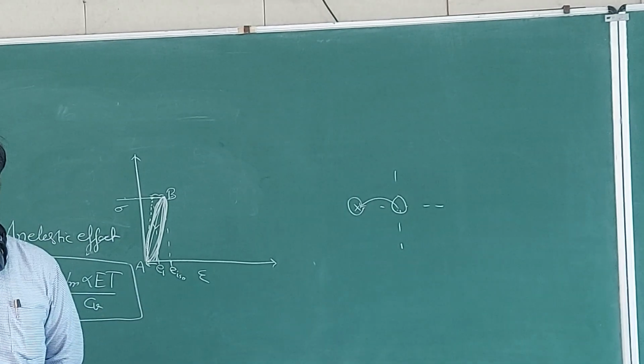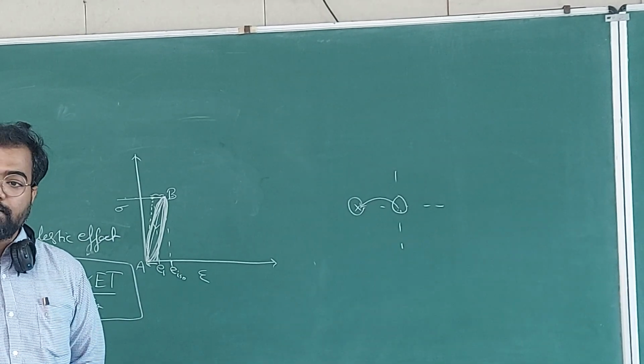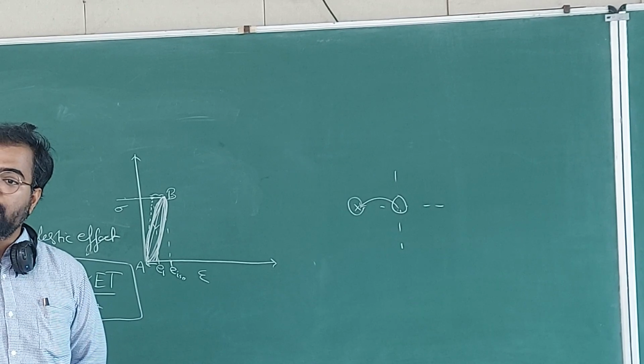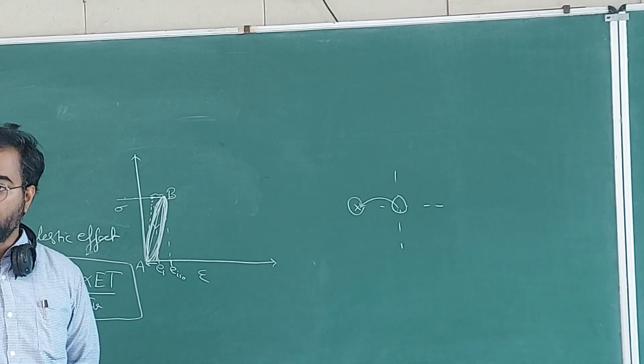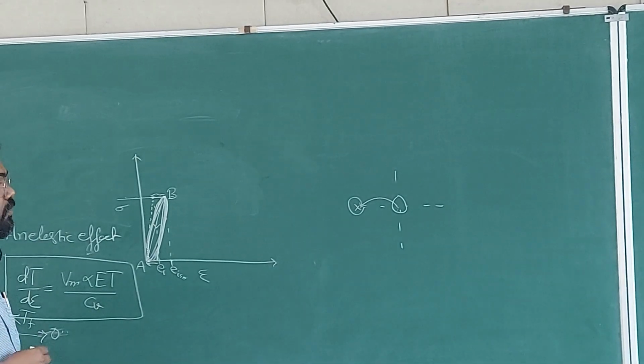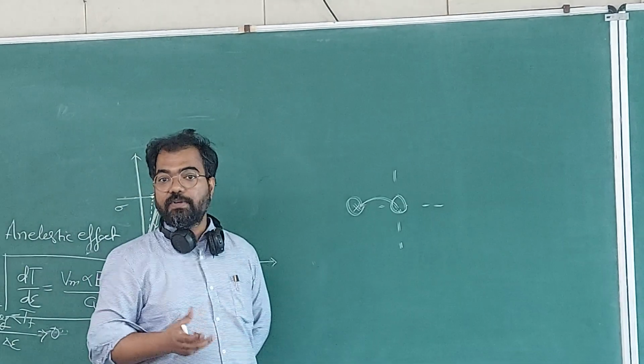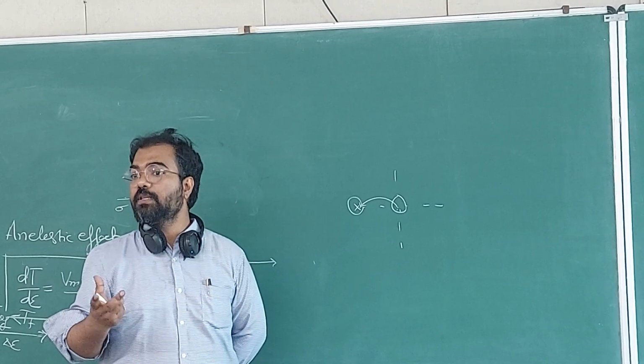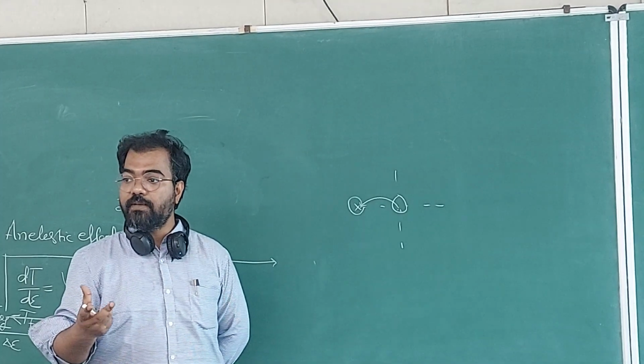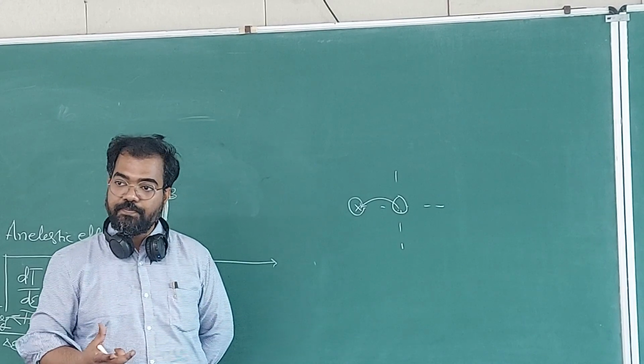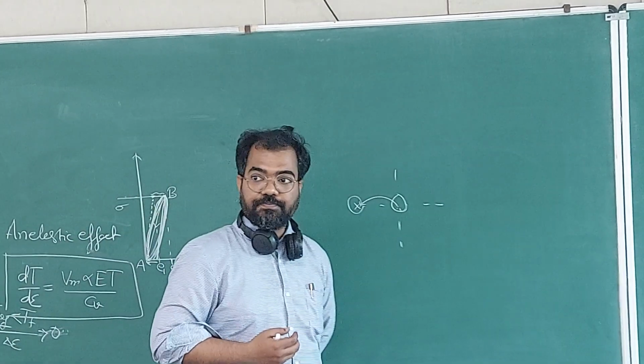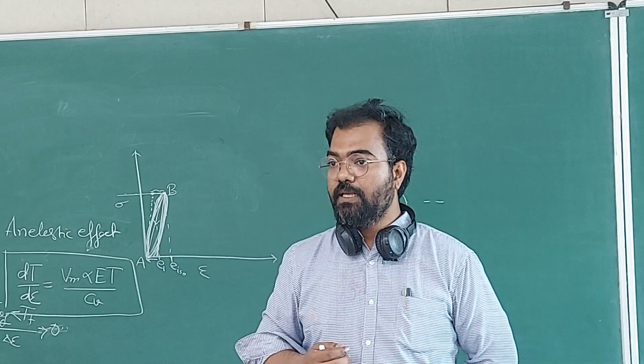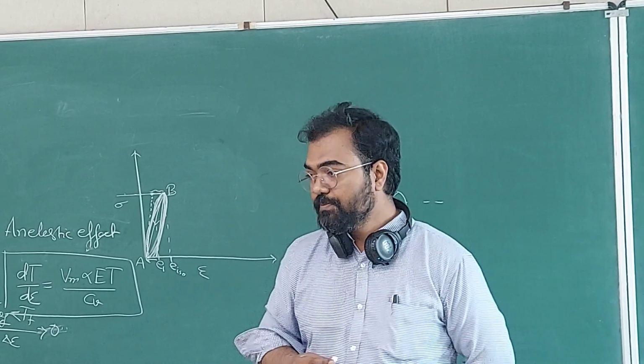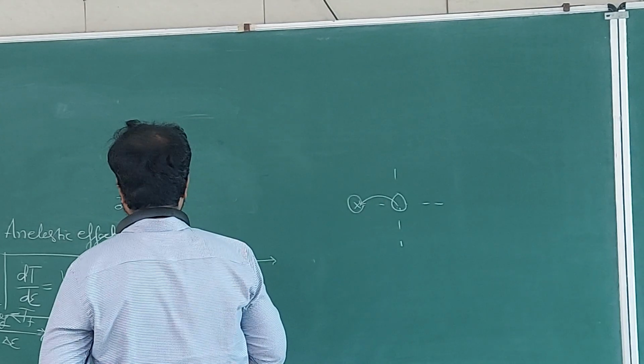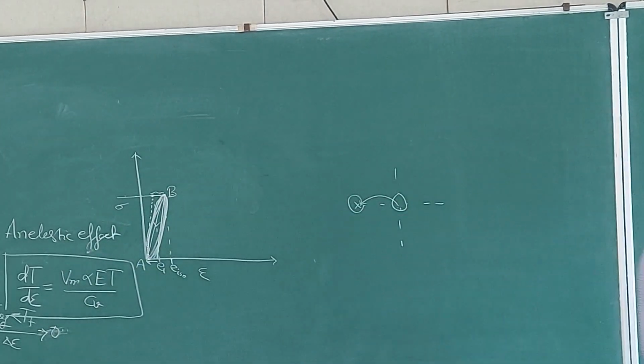Right? So this jump probability is a function of temperature. As you increase the temperature, the amplitude of jump and the frequency will change. So as you go lower, this amplitude is going to decrease, the frequency is going to decrease, the jumps are not going to be that many. Even if there are vacancies available, diffusivity is going down. Equilibrium number of vacancies also decreases with respect to temperature. Yes, that also happens. So that will also contribute to lower diffusion at lower temperature. You are right in that.